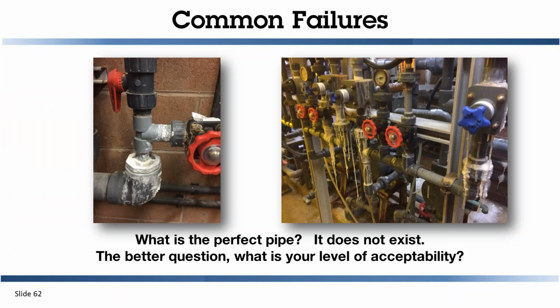Common failures, specifically in bleach piping, as you see here, is leaking of pipe at solvent cement joints. This is just bleach that is attacking the joints and coming out of the fitting. So what is the perfect pipe? It really doesn't exist. You're trying to balance the cost of the material with the lifetime, and most municipalities don't have an endless budget, so we're trying to create a system that has a long life at an affordable cost.